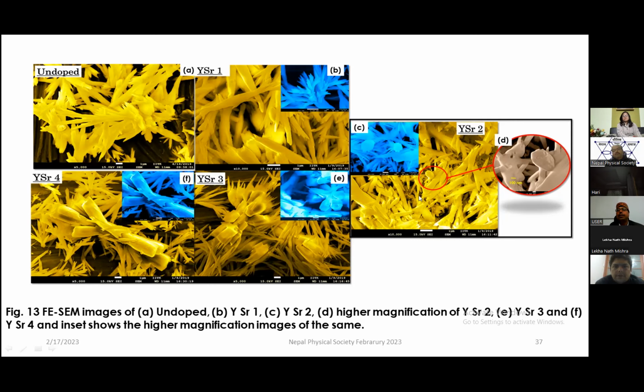This leads to an increase in the surface area. The surfaces that have developed are growing and popping up in some other direction, so it means the surface area is increasing. That is the beauty here. With the help of yttrium doping, it is increasing. And as we increase the atomic percentage of yttrium in doping, the agglomeration of the rods increases. They mix together, so the surface area does not increase further.